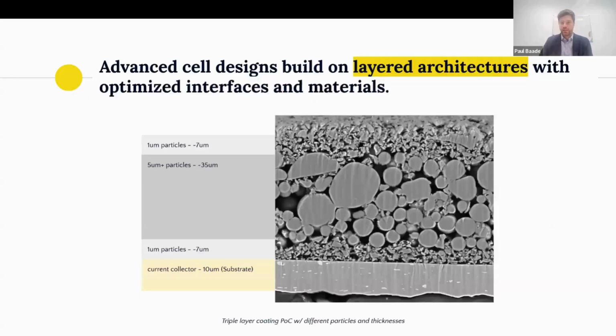So what does that look like? As an example here, this is a triple layer exemplary electrode where we demonstrate to cell manufacturers and customers that we can coat thick layers on top of thin ones. You can imagine the bottom layer right next to the current collector, for example, as a primer layer. We can coat large particles and small particles on top of each other, whichever direction you like. And keep in mind, those 3 layers are all coated at the same time, simultaneously.